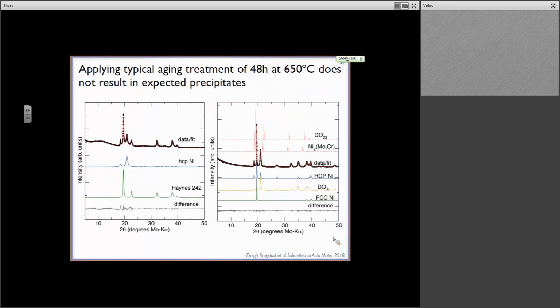Okay, so what we did, we know that this is well known for commercial alloys, coarse-grained alloys that have been properly processed. And so we applied the exact same heat treatment to our thin films of the same sort of chemistry. So we did this 48-hour heat treatment at 650 C, and we did not get what we expected. So what I'm showing you here in this X-ray data, over here is the as-deposited X-ray data, and here is our annealed X-ray data. And so here we see that we have, if we actually do a quantitative fit, like I said, about 50% of this HCP phase and about 50% of the expected FCC lattice. When we do the annealing, what we expect is this phase up here in the dashed line. Rather, we get what I'm labeling here as the DOA phase, which is that equilibrium structure.